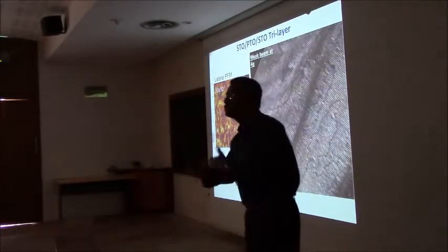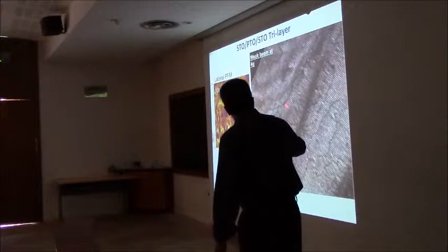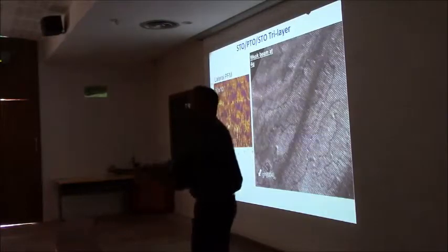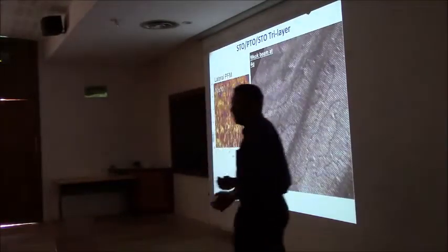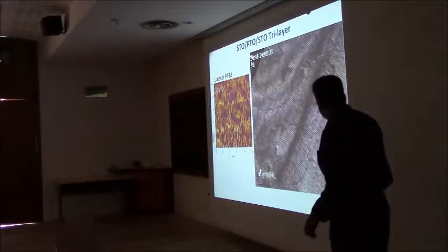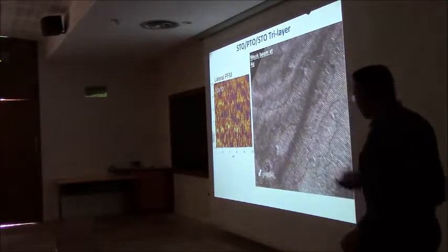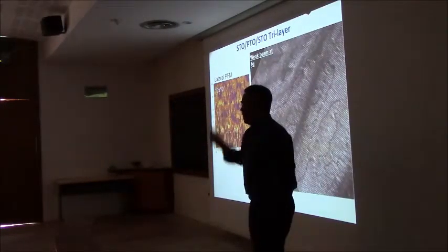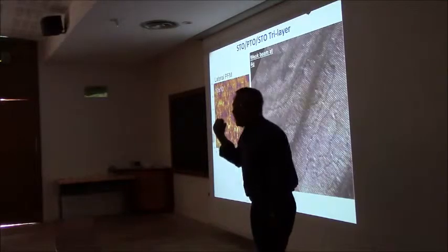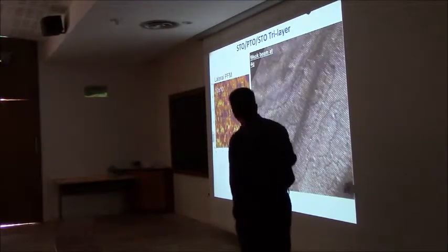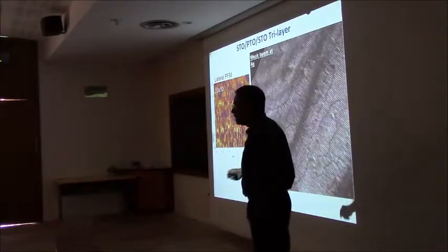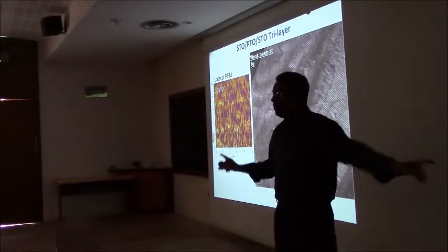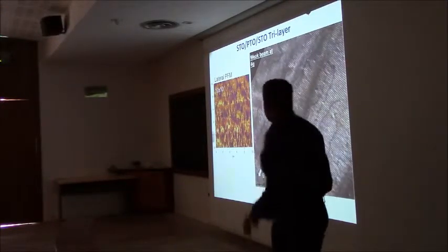And these look like antiphase domain boundaries, where from this side to this side, there's a shift of lambda by 2 of the vortex structure. Remember, there's a vortex, anti-vortex, vortex. You can shift them by half a wave. So that's what these boundaries are. And we're going to come back to it in a few minutes to understand what they do. It is very clear from piezo force microscopy. Alexei will talk about the imaging process next week. But from piezo force microscopy, you can see that the in-plane polarization component in these guys is changing by 180 degrees. It's going from this to this. We'll come back to it later.